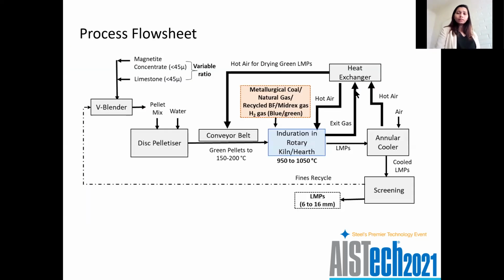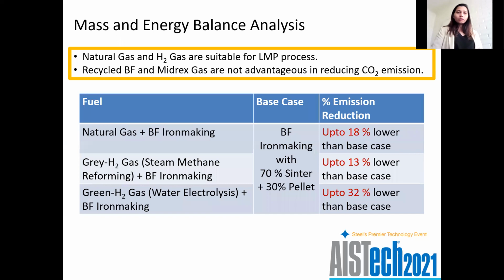Now, we have analyzed the emission for this LMP process by considering different types of fuel going into these kilns: coal, natural gas, recycled Midrex gas, recycled blast furnace gas, and hydrogen gas, both blue and green hydrogen gas. And then we compared the LMP process, followed by blast furnace iron making, with the base case, iron making in blast furnace with 70% sinter and 30% pellet. The results show that when the LMPs are made with natural gas and followed by blast furnace iron making, it will reduce the CO2 emission from the base case by up to 18%. With gray hydrogen gas, it's up to 13%.